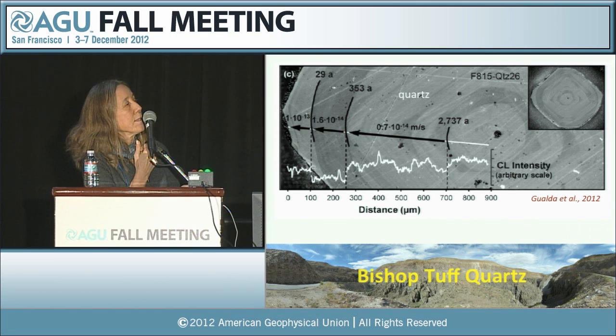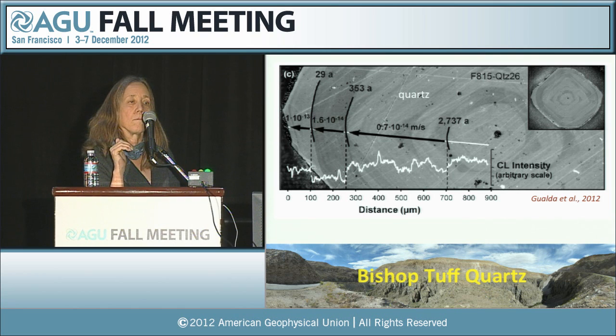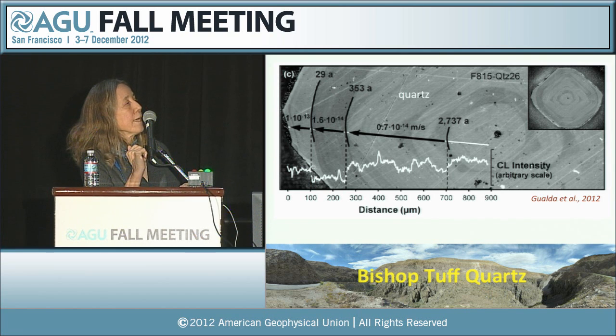And specifically what they've done, and you can see it here with the CL intensities, is they've looked at where there are steps in the CL intensity, here and here, for example, and then looked at the amount of time that's required for diffusion or relaxation of those profiles, assuming that they started out as vertical steps. And again, using the diffusion rate of titanium within quartz.